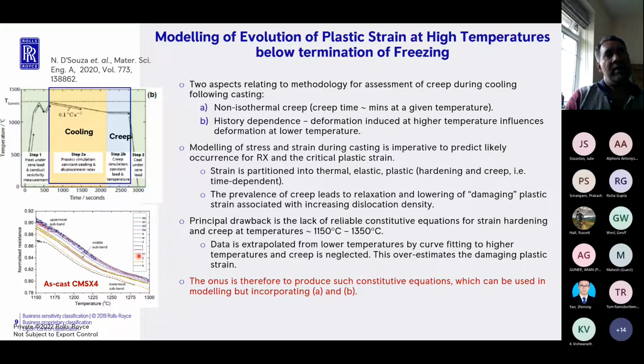Now, as far as investment casting and cooling of a turbine blade, if you want to look at modeling the creep strains that develop, there are two important criteria. The reason I say creep is because at temperatures of the order of about 1300, you have a very limited amount of hardening. The material is extremely plastic, and therefore it flows very easily. So creep is one of the main mechanisms by which you get deformation at such high temperatures.